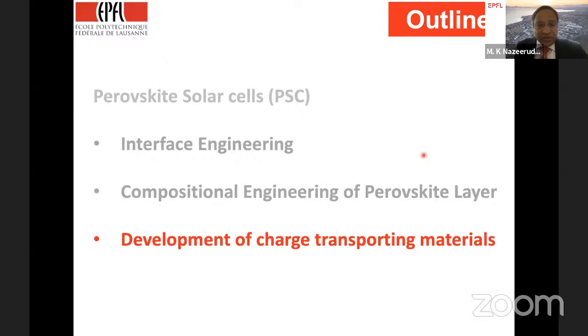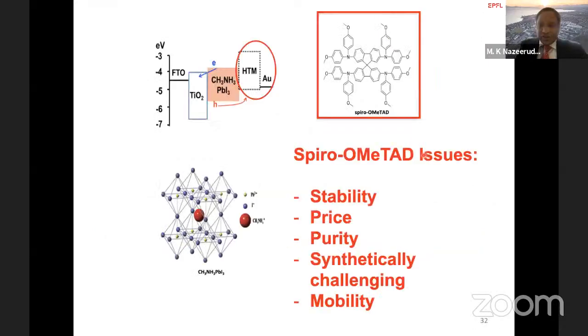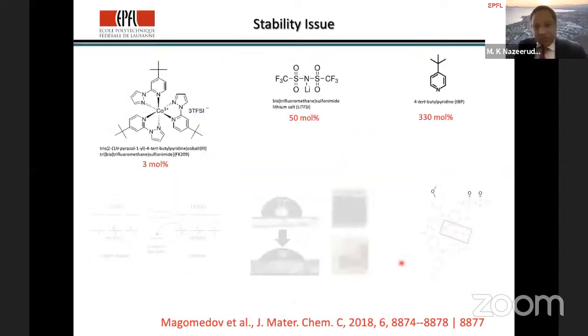So I come very quickly to the charge transport materials. As we have seen, we are building the perovskite solar cells encapsulated between the hole transport material and the electron transport material. We discussed in detail the perovskite composition. Now we go to the hole transport material, which is on top of the perovskite. So far, the best working hole transport material is spiro-OMeTAD, which has the following issues: stability, price, and purity. So these are the issues with this material.